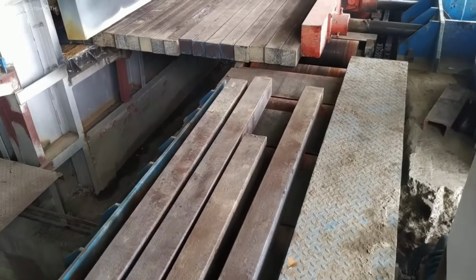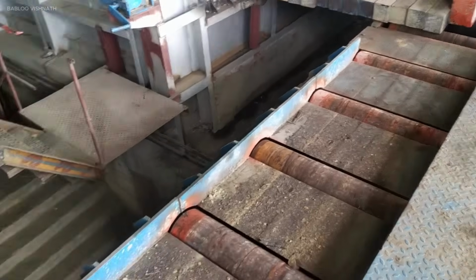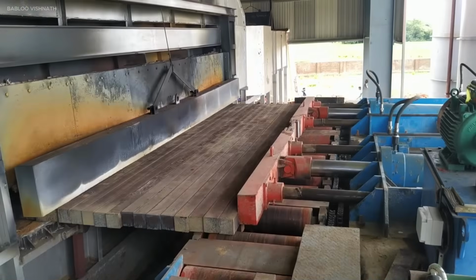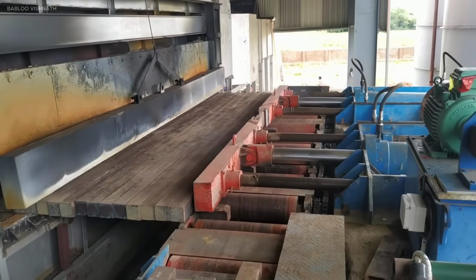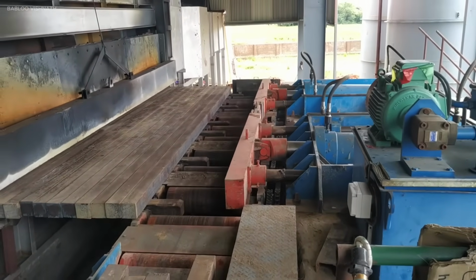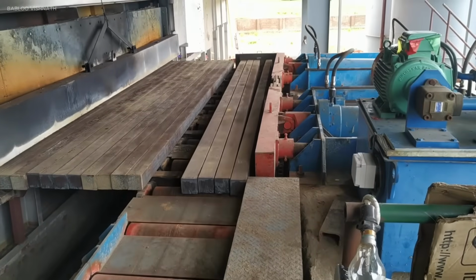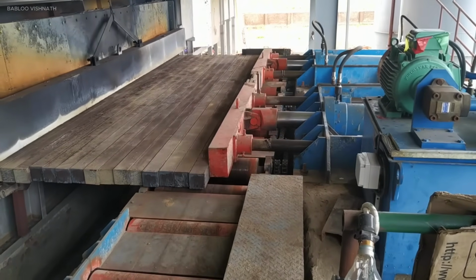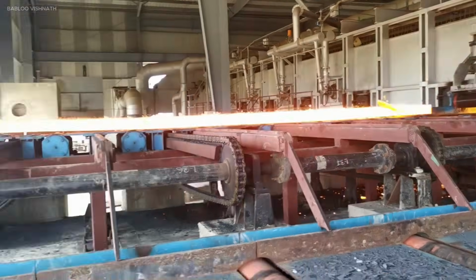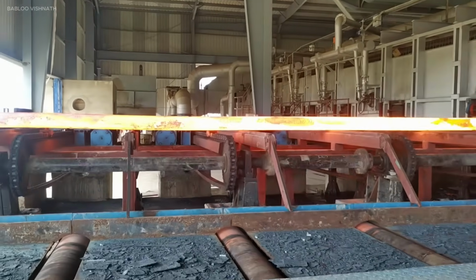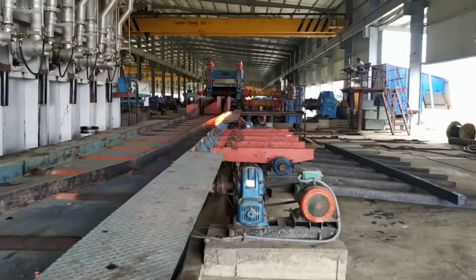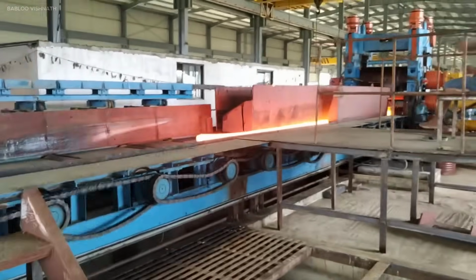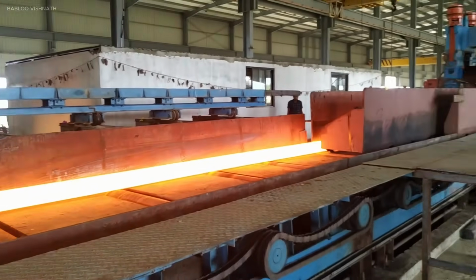In Nepal, KN Engineering heats billets to 1,200 degrees Celsius in a pusher-type reheating furnace. The red-hot billets exit the furnace and pass through a descaling box before entering the rolling mill. The material undergoes progressive reduction through roughing, intermediate, and finishing mill stands. Each stand consists of heavy-duty gearboxes and precisely aligned rollers to ensure dimensional accuracy.